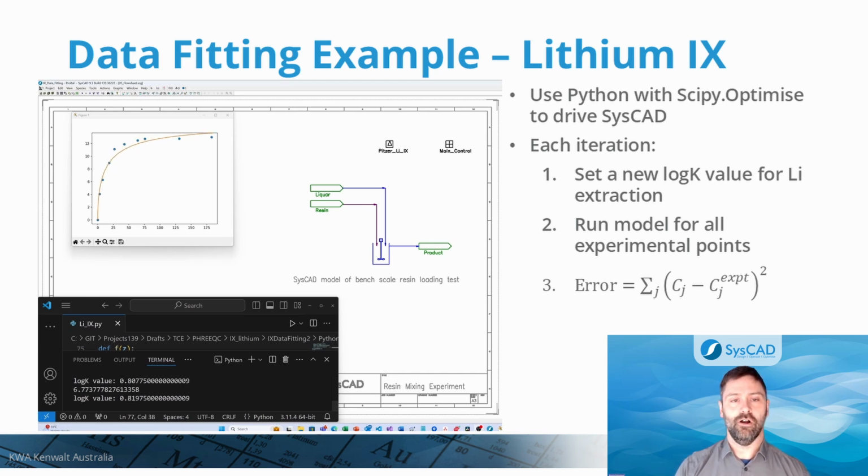By doing this for all rare earth elements, a competitive extraction model is developed, where the extent of extraction is influenced by the activity of the ion in solution. In this way, isotherms for different pregnant leach solutions can be predicted. This can significantly reduce test work requirements when a validated thermodynamic model of the system is available.